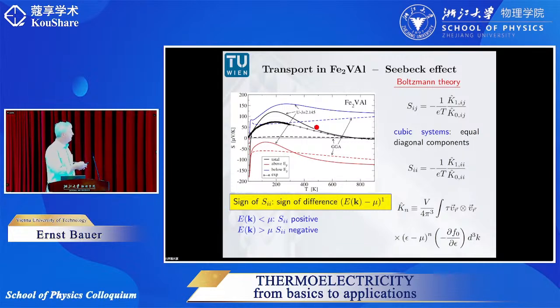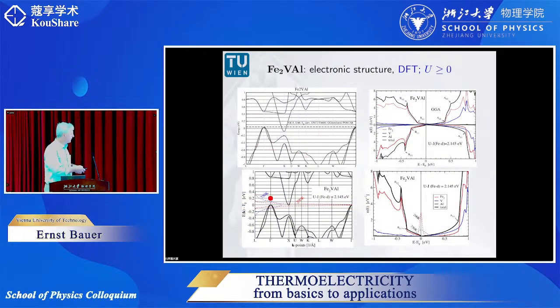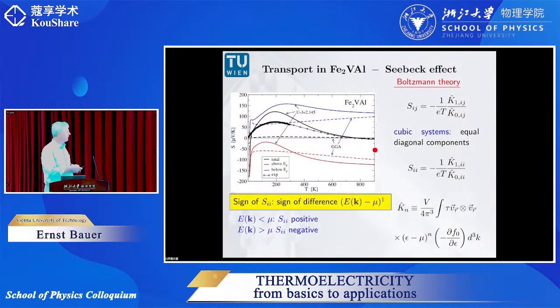And you can see when having this Coulomb correlation strength, at least the position of the maximum or the movement of the Seebeck coefficient through 0 can be represented. As we have seen on the previous page, electrons from this band are contributing, and holes from this band are contributing as well to the total Seebeck effect. So we have contributions from above and from below, and the summation of both effects reveals the entire Seebeck effect of the material.